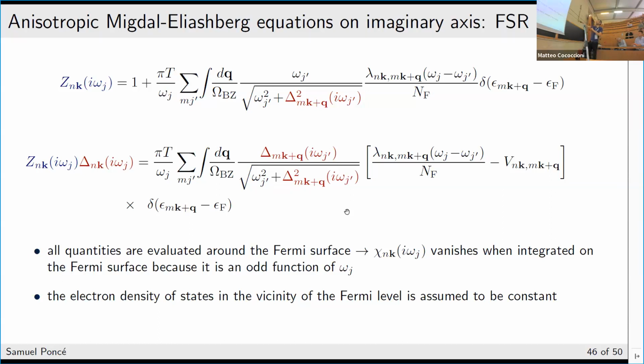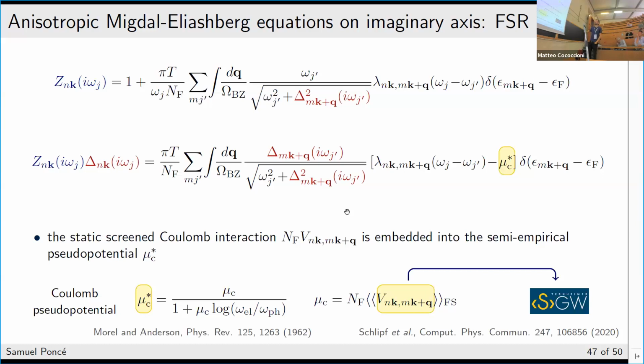Anyway, so in practice, this is also what we can solve in the code. Note one thing, you still have this term, which is this Coulomb potential, and this is still one number somehow. And so in the code, you will have to give this number. It has some typical value, but it's something that you have to input to the code. However, one can actually compute this, and you can use codes to compute this electron-electron potential and interaction, and then you can plug that in here, or you can keep the generality, and this hasn't been really done, but you can basically compute the full result, put it there, and then try to solve it.